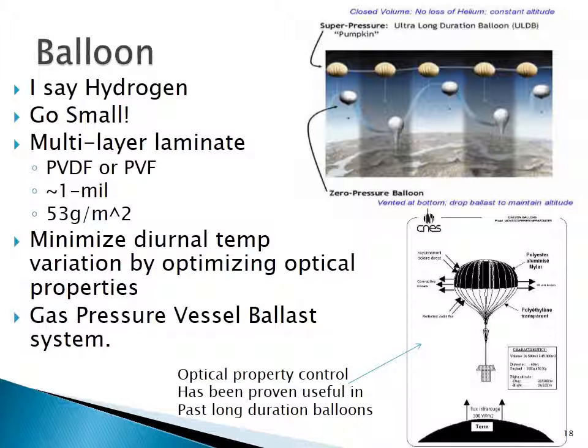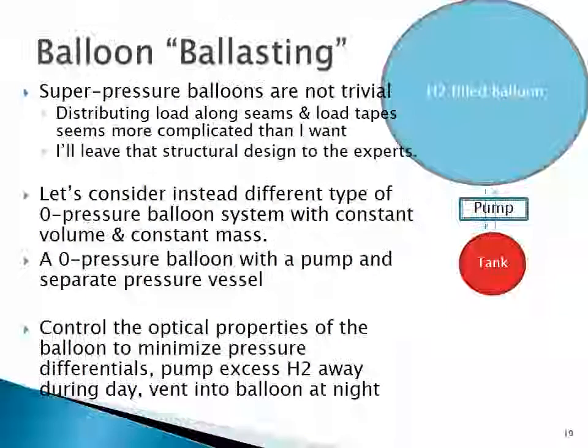So finding that sweet spot of emissivity and solar absorptivity is an interesting area of research, because by doing that you can find out what is the optimum treatment for the skin that minimizes the temperature differential day to night, because minimizing the temperature differential minimizes the volume of gas you have to store to maintain buoyancy. So in my system, that buoyancy is maintained through an external tank, and you could use the same system to control the altitude by bringing it up and down.